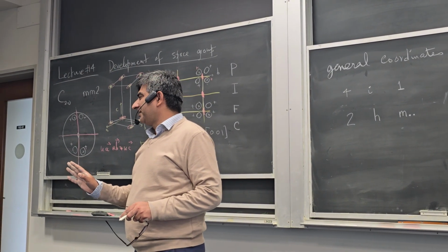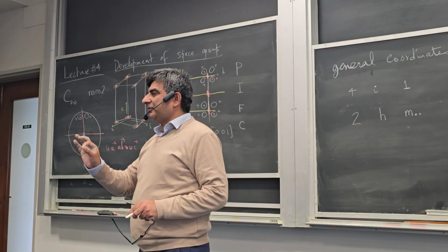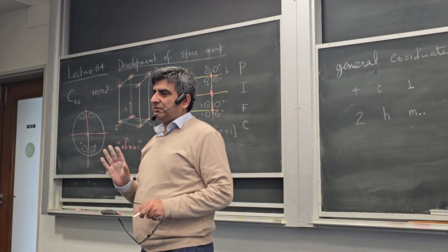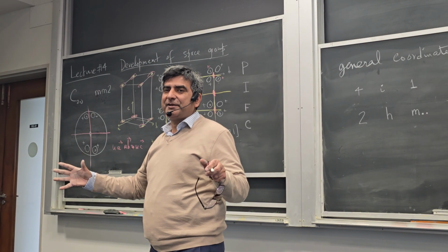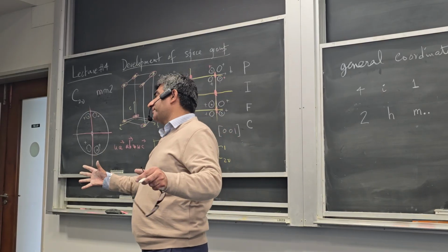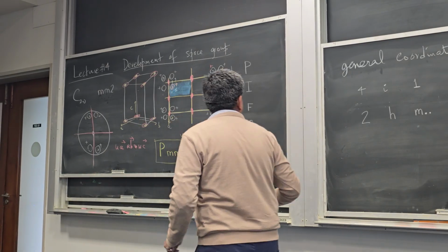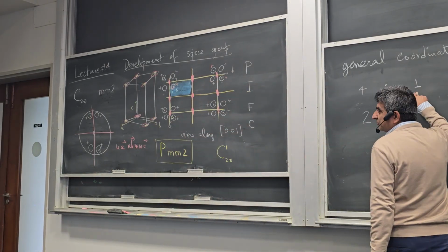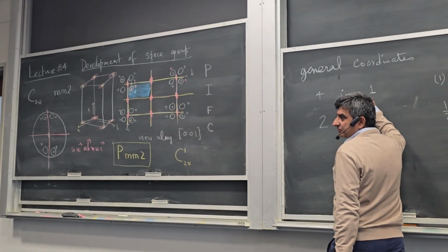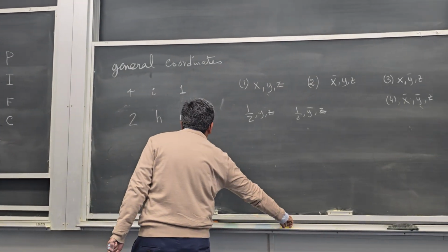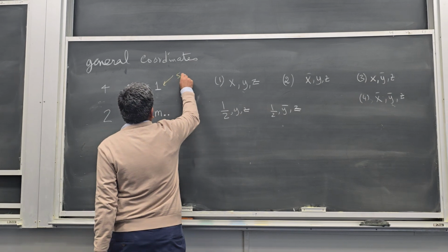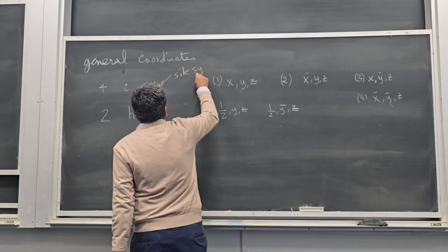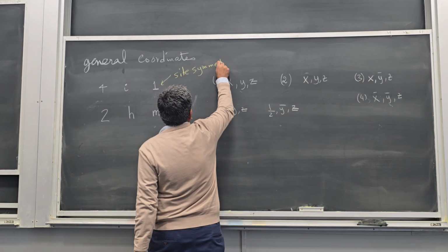It has no symmetry constraints on the general position. But you need a large number of points there because you have to respect the overall symmetry of the space group. This is the positional symmetry, called the site symmetry, and the site symmetry of the general point is trivial.